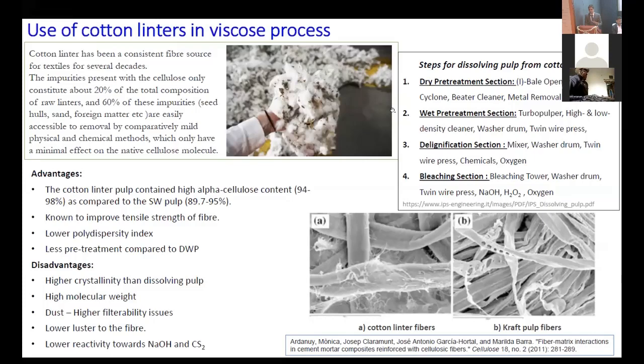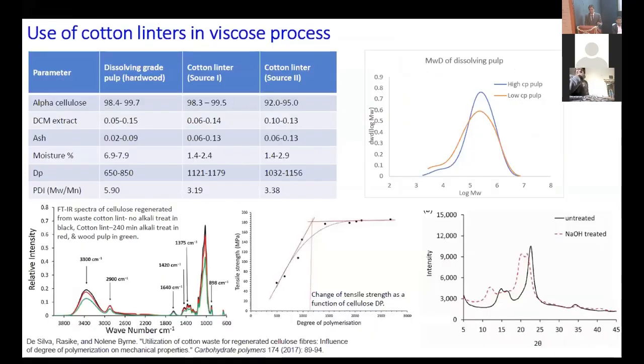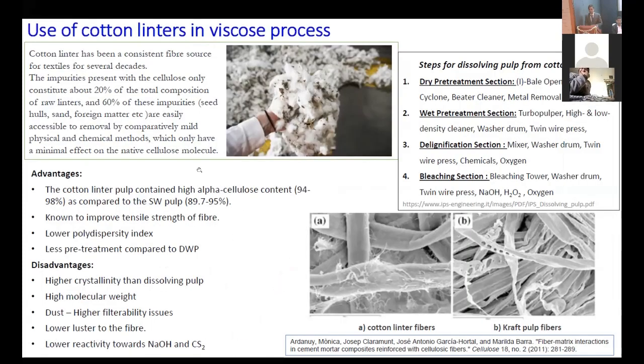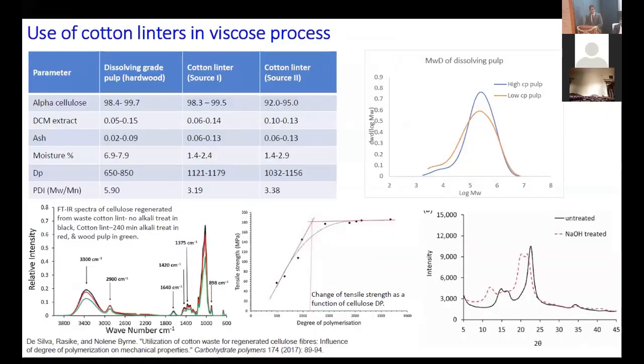Cotton has a very simple pulping process, unlike the other processes. The cotton chemical pulping process uses fewer chemicals and less stringent conditions for processing. So if we see the comparison of dissolving grade pulp with cotton linters, cotton linters have very high alpha cellulose content. It has low DCM extract, ash, moisture, everything is less. The only problem is with the DP. DP is very high in cotton compared to the other dissolving grade wood pulp. And this is the major challenge that we face.